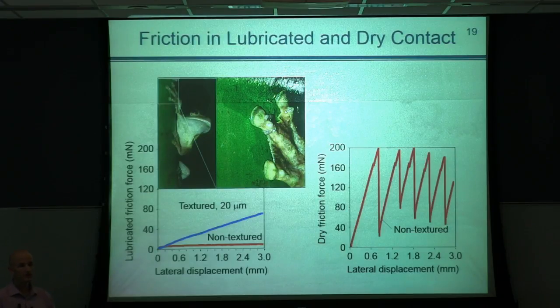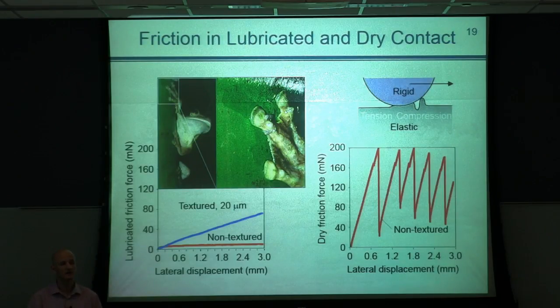We were really surprised to see very interesting results in testing dry sliding conditions. So what you see here is the performance of a smooth surface sliding against the substrate, and we can clearly recognize stick-slip motion, which can be explained in the following way. When we have a rigid surface that slides against the elastomer, which cannot really slide in an accepted way, the surface behind the contact is in tension, the surface in front of the contact is in compression, so it buckles, and then a small wave is created in front of the contact that runs in between two surfaces.